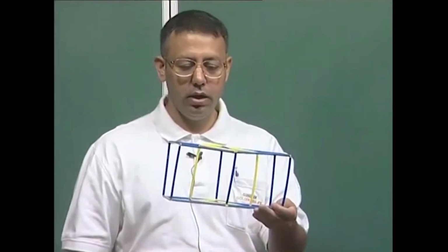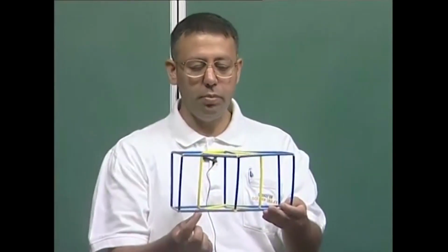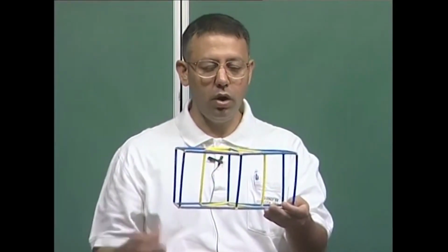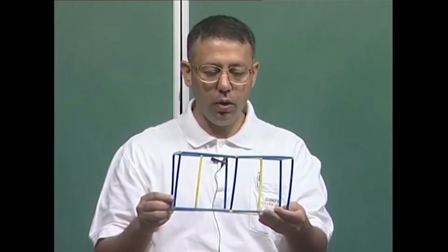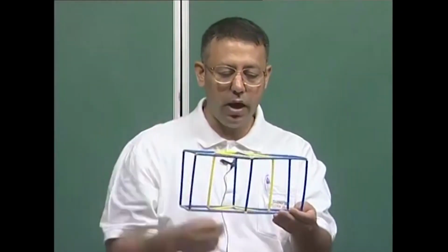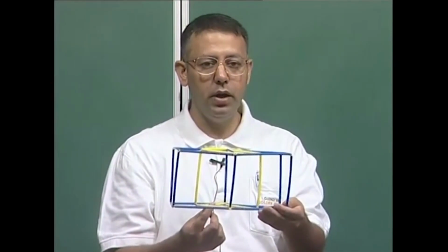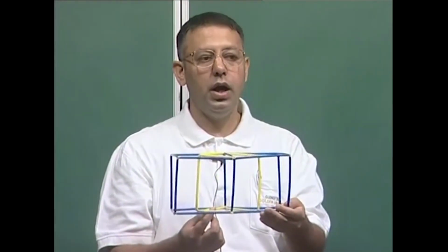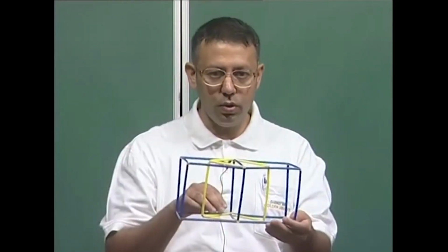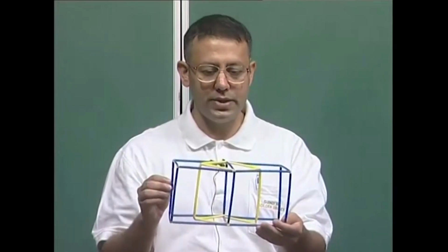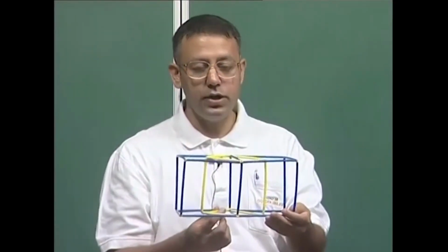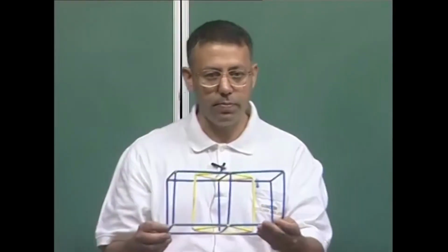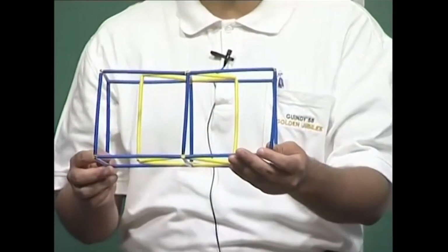So, you can see here that I have introduced these two centering points at the top and the bottom, and what I have done is made an alternate choice of the unit cell, and this alternate unit cell, which is marked in yellow, is a simple tetragonal cell. As far as the cell goes, this is a lower symmetry cell than the cubic cell, which is blue, but it is smaller in size, as obvious from this figure. So, it is a smaller cell, it is a primitive cell, that means that there is only one lattice point per cell.